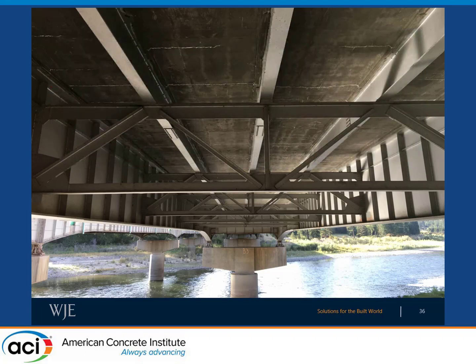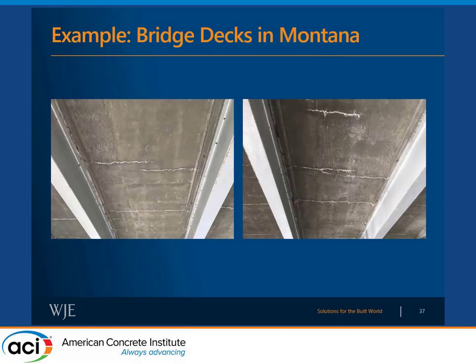But going back to this photo, when we used the drone, we could actually see quite a few patterns developing on the underside of the bridge decks. And this was a pattern that we saw repeatedly over many of the bridge decks that we looked at. So it became very clear to us through several of these investigations that the cracks initiated pretty early on, right over the beams, and then started to progress inward, where eventually they'd come in pretty close contact and they'd sort of jump. So we started calling these jump cracks.